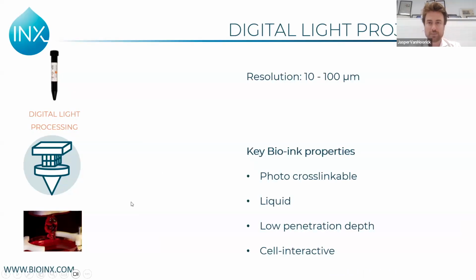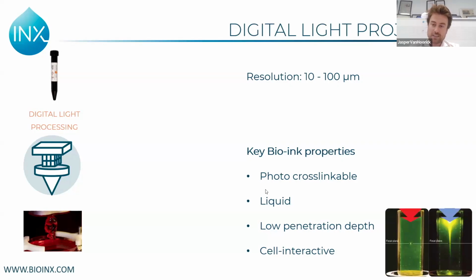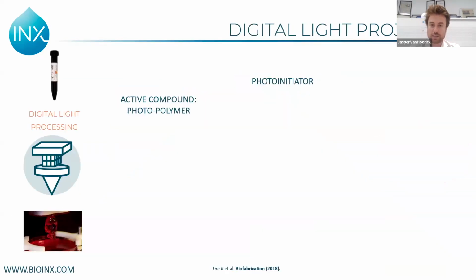a 3D printed construct. What's important here from the bio ink, your material needs to be photocrosslinkable. In this case, it needs to be liquid because your print bed moves inside of it. And what's crucial here is that the light should have a low penetration depth, because as I showed before, in conventional single photon processes, you would have a reaction everywhere along your beam path because every photon has the required energy to induce the reaction. So therefore, it's important that you limit your penetration depth, otherwise your resolution in the Z direction would be completely lost. And this you can do by playing around with the formulation.